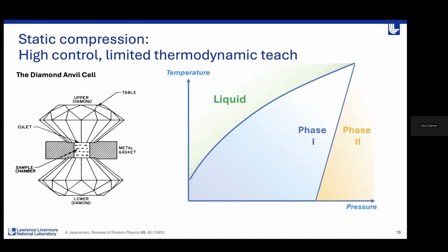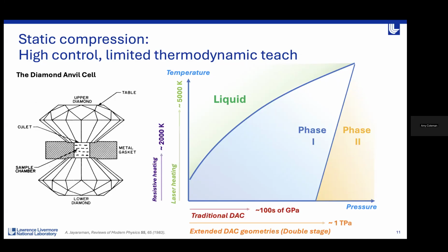Now, not all diamond anvil cells are created equal. We have traditional diamond anvil cell or DAC geometries, which reliably can get us to pressures in the hundreds of GPa in the lab, setup dependent, material dependent, but we can very reliably access this regime, which is absolutely fantastic. But we also have extended DAC geometries, so things like toroidal DACs or double stage DACs.